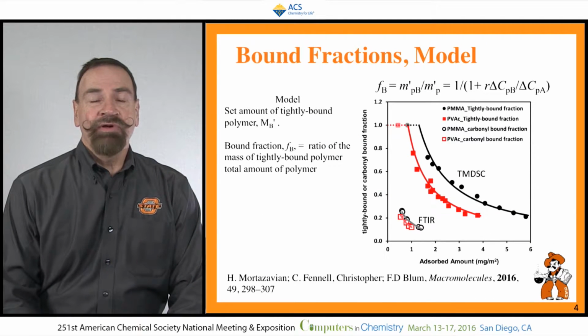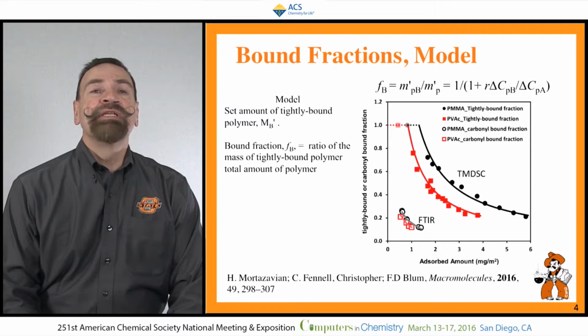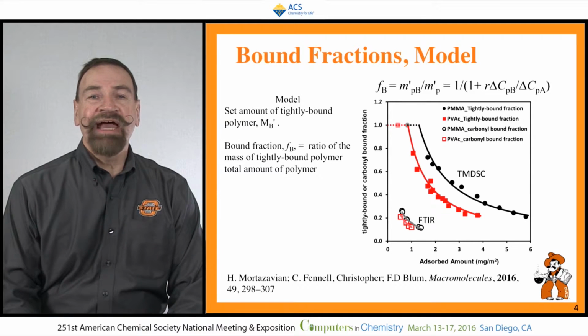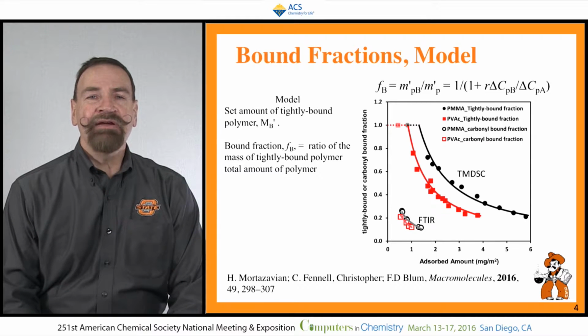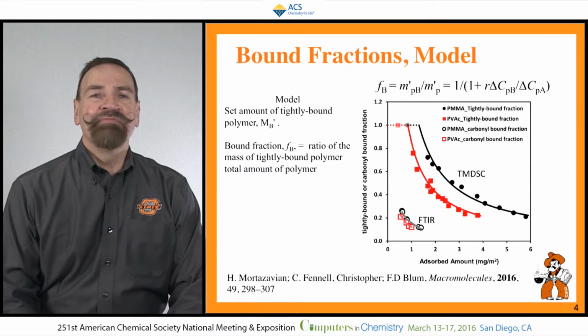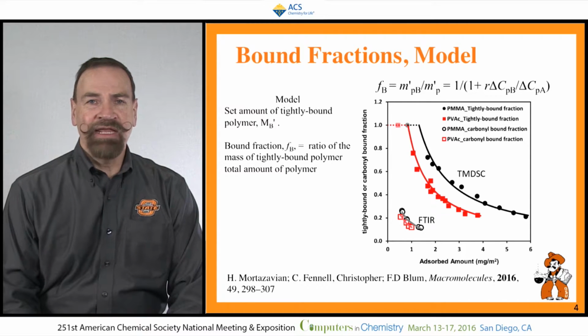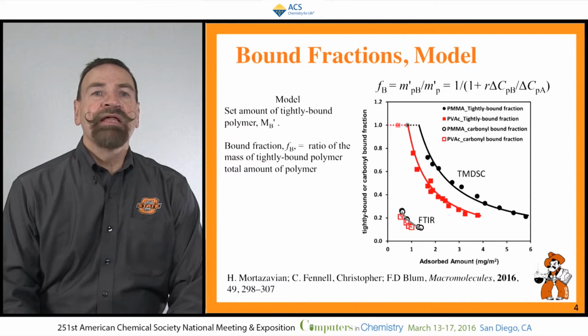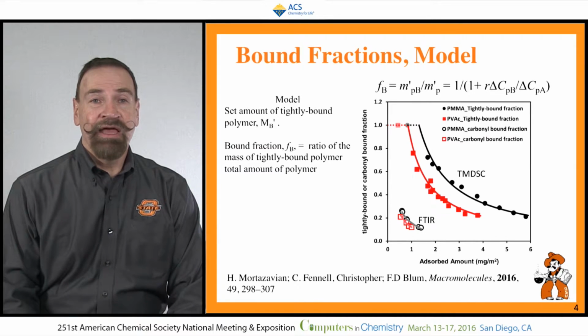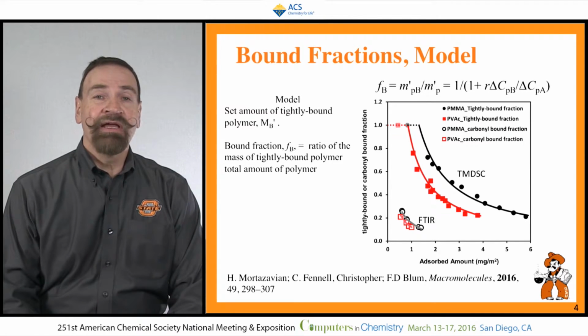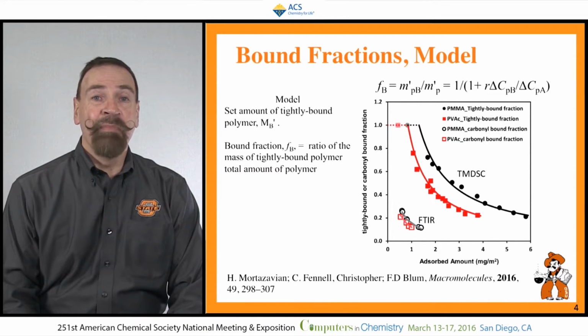One of the things that we can do is add bound material to the surface, and we can actually estimate how much bound material we have. Here in the red squares are the amounts of bound material from the differential scanning calorimetry experiments. The fraction of bound material is calculated by saying that there's a set amount of tightly bound polymer, and then when I add more polymer, the polymer that I add is loosely bound. You can see that the squares fit the line, or the experimental data fits the model quite well.